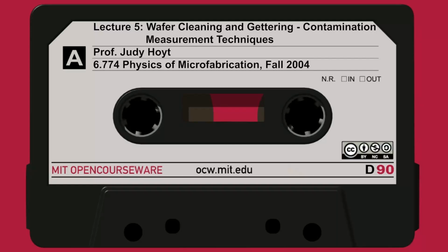Silicon, of course, is going to be large because it's a silicon surface. There's a lot of chromium on this sample. Look at the peak labeled chromium, and a fair amount of iron. So the nice thing, it gives you a broad spectrum. You can just shoot the X-ray onto the surface in about a 1 centimeter area, and you can immediately survey in the transition metals what's on that surface. Very useful and commonly used technique.